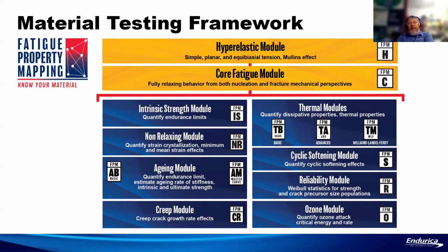We can measure the fatigue limit. We can measure the strain crystallization, which has an effect on mean strain effects. We can look at aging of the rubber. We can look at time-dependent behavior, like creep. We can look at the dependence of rubber fatigue on temperature, self-heating and temperature gradients. We can look at cyclic softening. We can look at ozone attack. These are all options that we can add. It's a very modular framework, and you just do what you need, but very scalable.